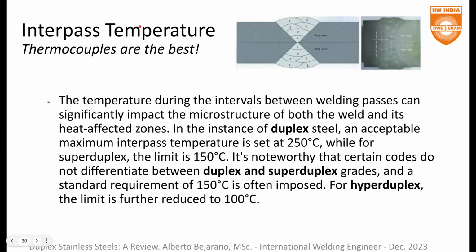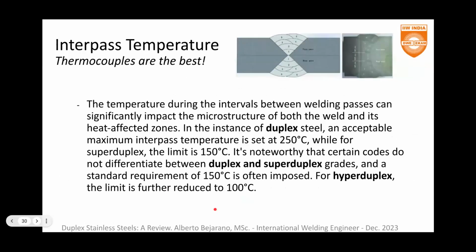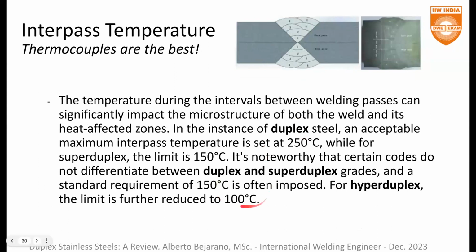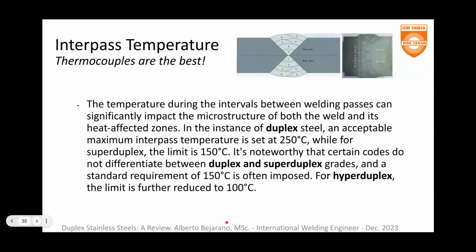So in duplex, which means the first members, lower alloy in the family of duplex stainless steel, we can use 250 Celsius. If we talk about super duplex, we can talk about 150 Celsius. Okay, 150. And in the case of hyper duplex, the recommendation is 100. Okay, 100. This is very important because this interpass temperature